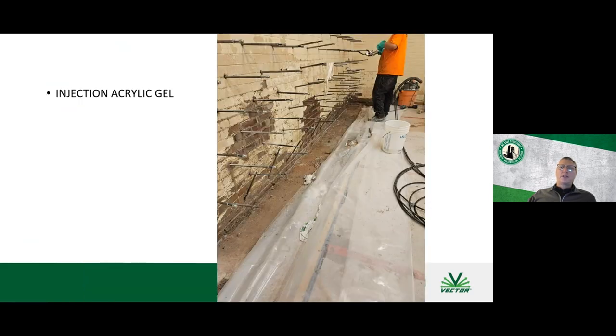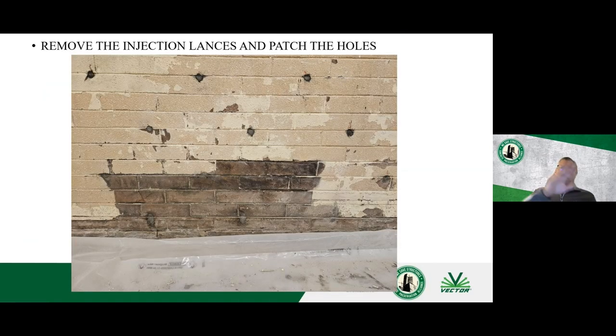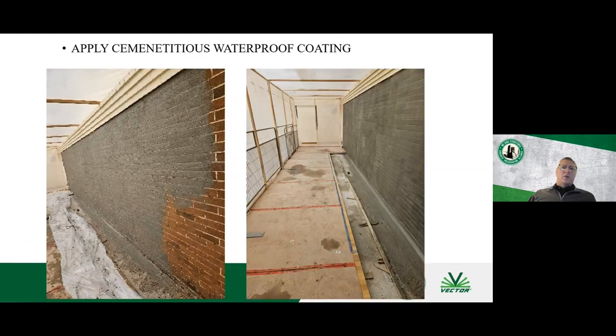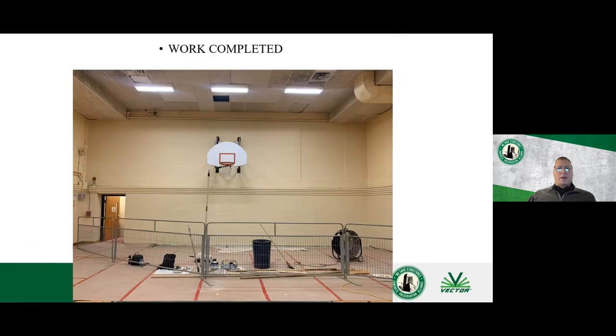So you go along, you inject all of these. You use a certain amount of time so you know how much material you're putting in. You want to make sure you get enough thickness. Then you remove your lances, repair your holes. And then they're adding a cementitious waterproof coating on top of the masonry. So they're adding a secondary layer because even though you're creating that barrier, this is additional protection for the new gym floor that was being installed. And that's what the project looks like nearly to completion.